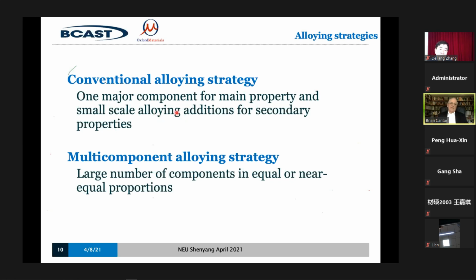And that's what happens. So nickel superalloys, for instance, are basically nickel because it's a high melting point metal, and it can be formed into those funny shaped blades, those aerodynamic blades. But it wasn't good enough until it was strong enough. So you have to add a certain amount of aluminium to make it strong enough. And you have to add a little bit of chromium to make it corrosion resistant. So that's typically what happens.